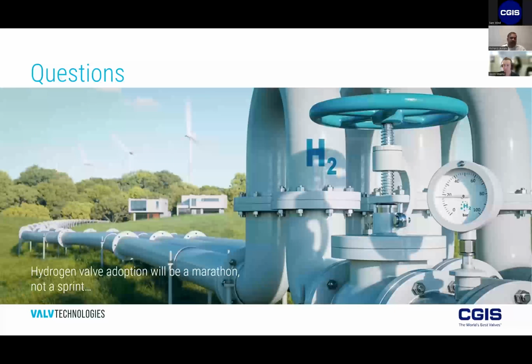If we think about power generation, for example, where you have high pressure steam going through a valve, I don't think factories test to 500 Celsius. It's possible, but most factory acceptance testing is just done at ambient, and that's not really reflective of what the valve will see in service. That's the other reason why we have pressure and temperature tables. We compensate for that by over pressurizing during the hydrostatic tests. If a shell test is done at 150% of the cold working pressure, it means that as the temperature rises, the maximum allowable pressure starts to decrease, and that's why you would over test a valve with an ultra high pressure to compensate for the temperature aspect of it. So standards are just baselines. They don't really reflect what goes on in the field.